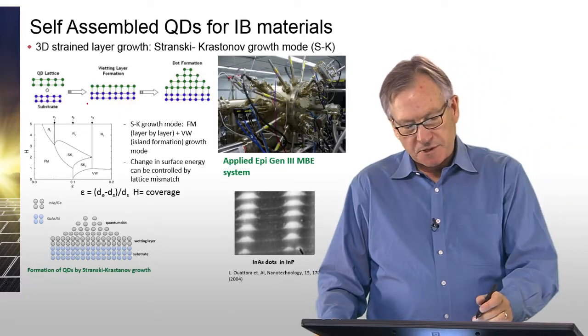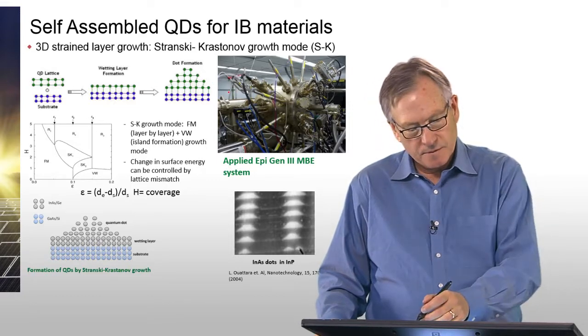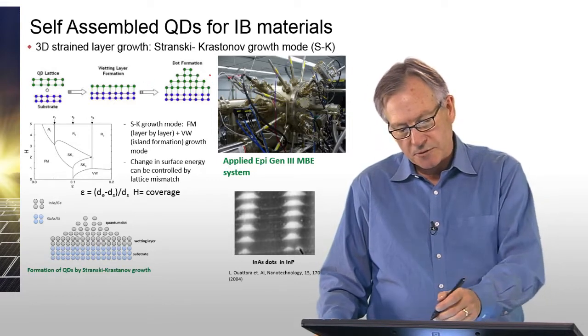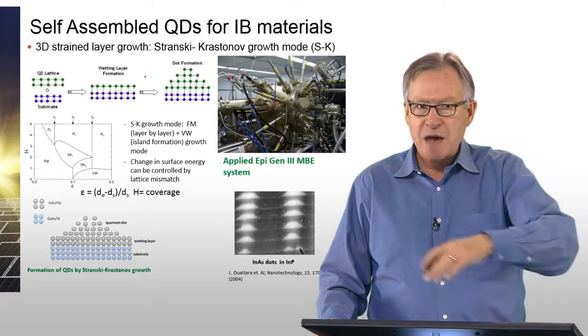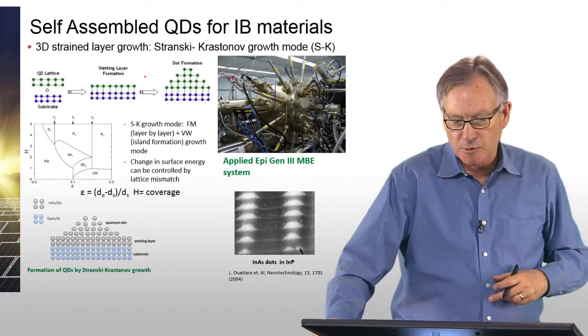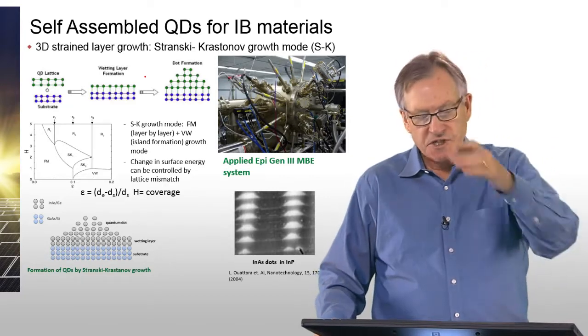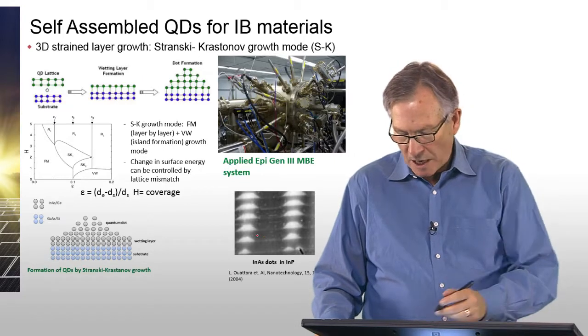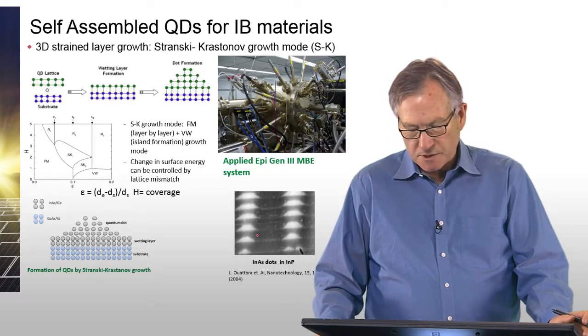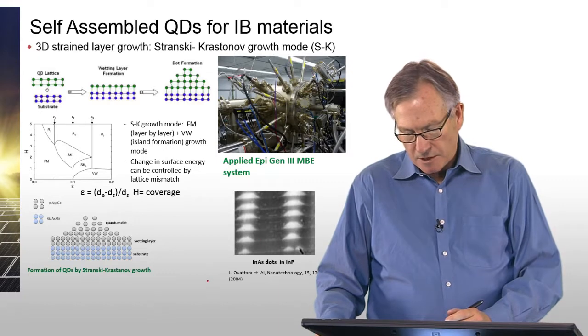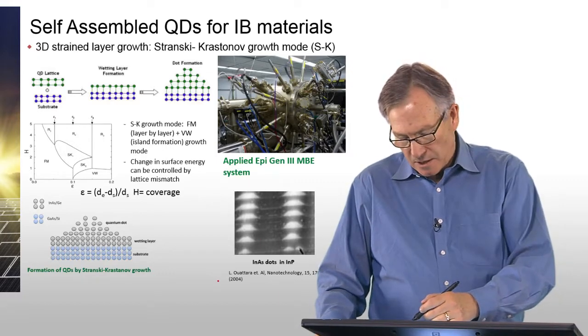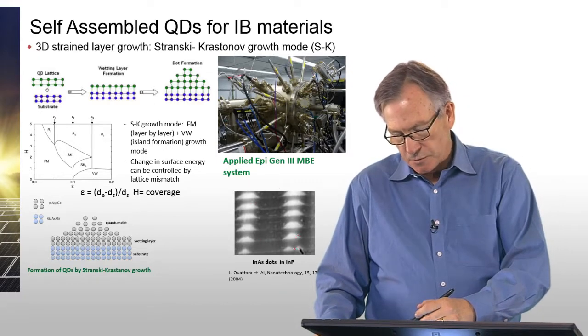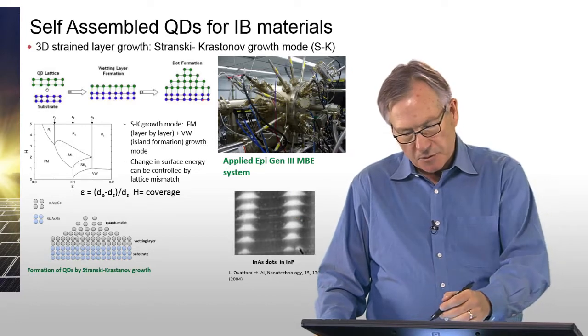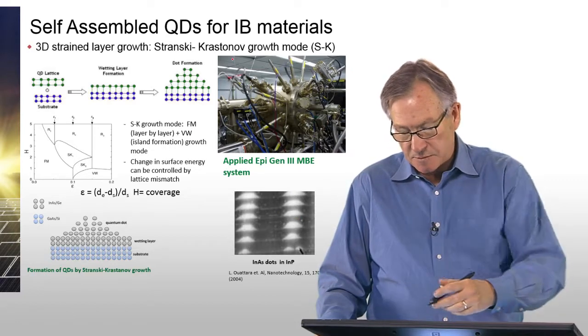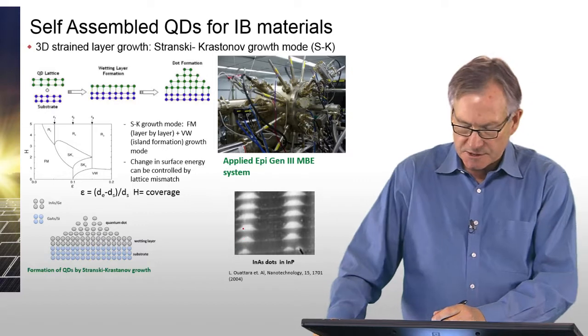And so you can grow these epitaxially. You grow first a layer, a wetting layer, and then it forms a three-dimensional structure. And then you cap it again with another layer of gallium arsenide. And you can do this successively. And what's shown on the right here is a structure that was grown by a group in Spain, which repeated this process many, many times, and the dots line up on top of each other.